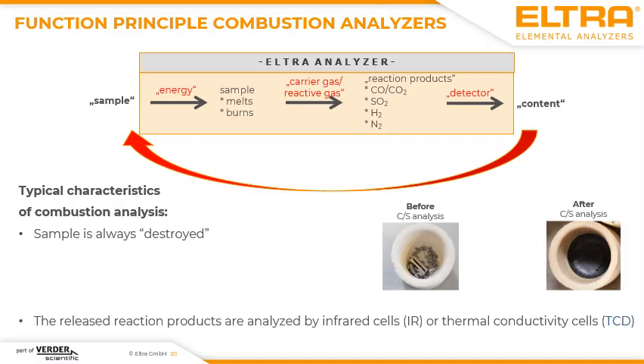By the carrier gas, you maybe have an oxidation effect or you have just a transporting of the sample. Our typical reaction products are carbon monoxide, carbon dioxide, SO2, hydrogen, and nitrogen. These gases are transported by the carrier gas to the detector, and then you get an element concentration. In case of carbon-sulfur analysis, please be aware that this kind of analysis is always a destruction of the sample, which means you start with a maybe powdered sample, and after the combustion you have just a residue which can no longer be used for other analysis steps.